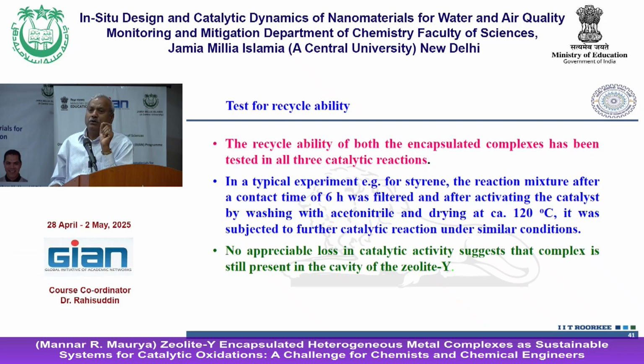This compound, or these catalysts, are very good and recyclable. The reason is that they are recyclable under the reaction condition, and that is important. When you heat excessively, definitely a compound has to decompose. But under reaction condition, meaning 80 or 100 degrees temperature for the catalytic reactions in the solvent, the compound is not decomposing at all, because it is entrapped in the cavity.